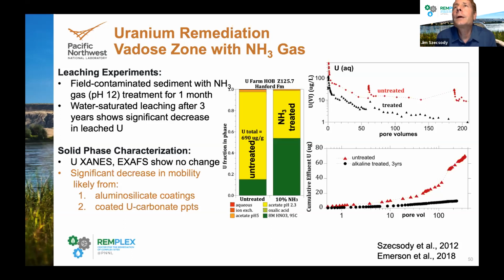The 5% ammonia gas raises the pore water pH to about 11.5, and aluminosilicates dissolve, things like montmorillonite, illite, muscovite. And over months, as the pH neutralizes, other aluminosilicates precipitate. So that's the main geochemistry that happens. Now, in terms of uranium, what we think happens is uranium surface phases are coated by these aluminosilicate phases.